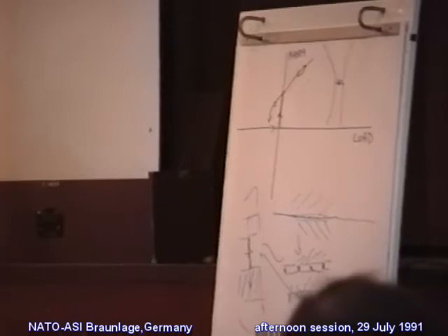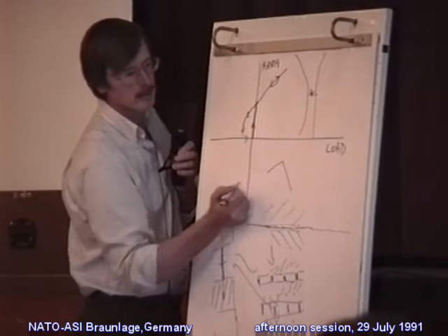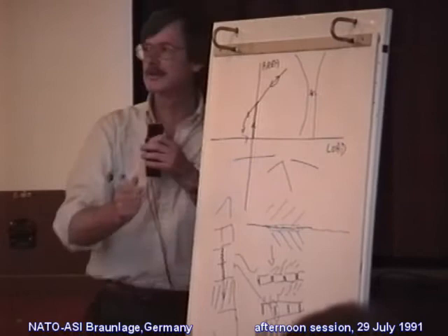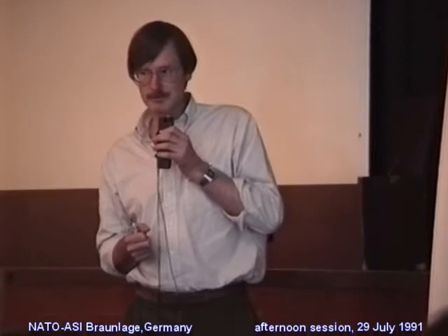I think the point about crack stability in fracture mechanics terms is it's a geometric thing. So because something is brittle doesn't mean that the crack is unstable. You can do chevron cracks, which I can't draw in bars, so the shape is like this. And so quite brittle materials can be made to fracture stably. And of course, Professor Tabor showed the peeling experiment, which I think is stable, at least at a fairly macroscopic level. And it's really only the special geometry, I think, of the sphere on the flat case where you get these jumps.